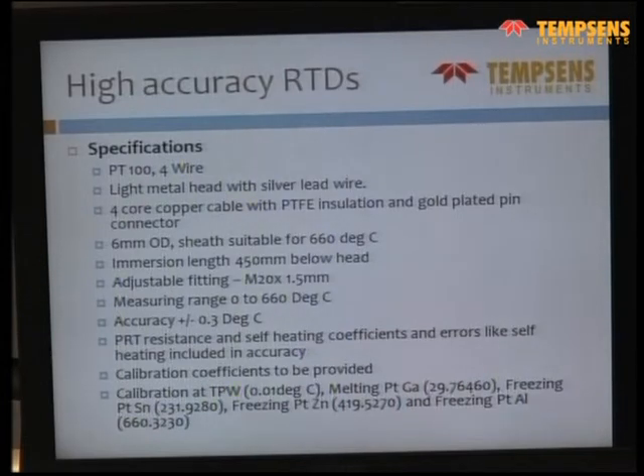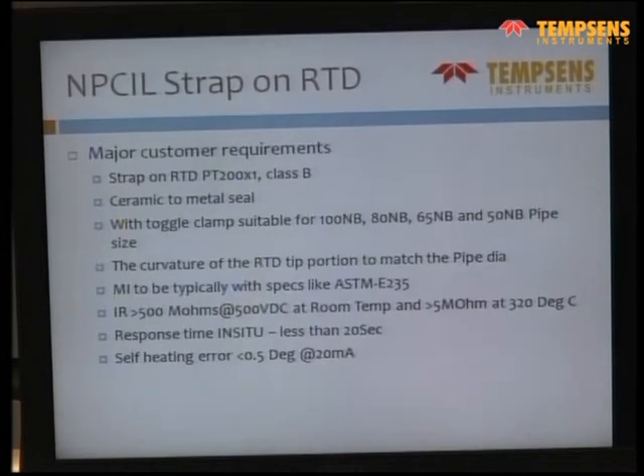So these are special RTDs which we have to offer with 0.3 degrees accuracy from a measuring range of 0 to 660 degrees centigrade. This can only be done by having a special curve for each RTD. So each RTD was checked at 5 fixed points, and then a special curve was offered to the customer so that he can get it in this accuracy range. And there was special arrangement made so that the drift is minimum for these RTDs.